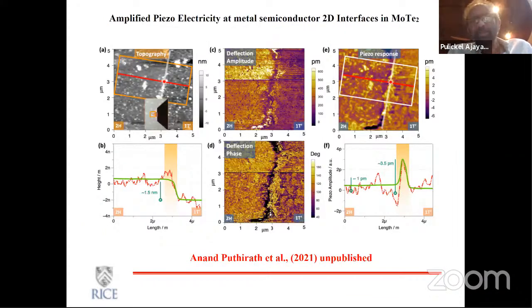Not only that, very recently, it's actually unpublished work, we were seeing that if you're looking at the piezoelectric behavior of these lateral structures, then of course the 2H is slightly piezoelectric and the 1T not. But we were seeing that at the junctions, you have an amplification of this piezoelectric response. And the reason for this is some kind of charge transfer that is happening between the semiconducting and metallic interface at the junction. And again, remember, these are all essentially in the lateral direction, because you are looking at a single unit thickness of these types of structures.